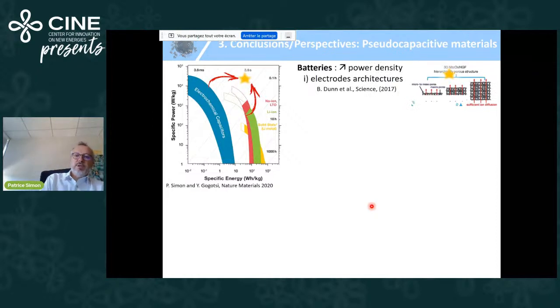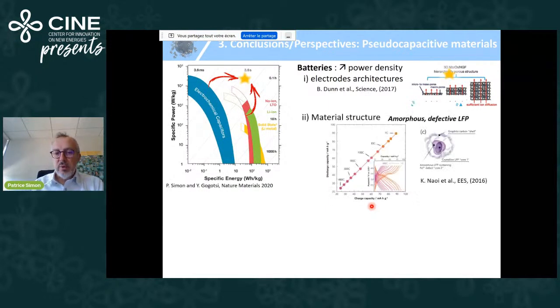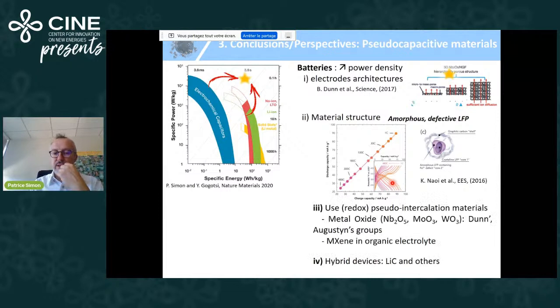And now, if you have a look at the battery side, you can increase the power density of batteries by designing electrode architectures, like Dunn and Rolison showing in Science, by making some nanoporous electrodes with super high rate, even at super high weight loading. You can also play with the material structure and prepare defective amorphous lithium iron phosphate. This is work from Naoi. There is also very super work from Masquelier at LRCS in Amiens, which shows that by tuning the defects on LFP, you can increase the kinetics of the redox reactions. And what is interesting from this work from Naoi is that this sloping charge or discharge profile is due to the defective LFP. So you can also change the electrochemical signature.